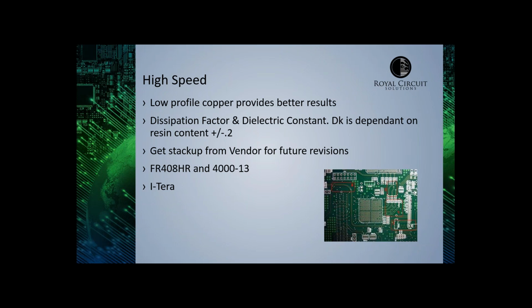The dielectric constant is very dependent upon how the material is made. When we do our impedance calculations, we still use one number, but if you really dig into it, you'll see it'll go between there. So the higher the resin content, the lower the dielectric constant, but it'll also have a higher dissipation factor for higher resin parts. Typically, thicker cores have higher resin content than thinner.